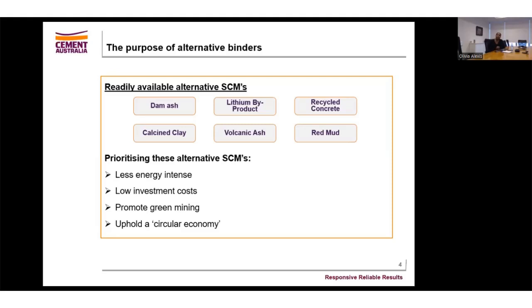So the way in which alternative binders will be prioritized, I've named a few. If we look specifically at dam ash, or if we look at calcined clay, you can compare the two and say that dam ash will be a more viable alternative binder. For one reason in particular, it's because it's a readily available binder, and it will have low energy in order to process it when comparing it to, say, a calcined clay. To process calcined clay, there's a significant amount of investment cost, and it wouldn't necessarily be upholding that circular economy when comparing it to dam ash, whereby the material is just in the dams, or for instance, looking at red mud, whereby you're using a waste material and you're recycling that. So that is what upholding a circular economy is.